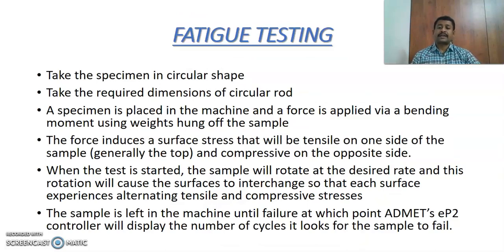We have to take the material in the required size and dimensions. The specimen is placed in the machine and the force is applied via a bending moment, and the force induces a surface stress that will be tensile on one side of the sample, and compressive on the opposite side. When the test is initiated, the sample will rotate at a particular rate, and this rotation will cause the surfaces to interchange, so that each surface experiences alternating tensile and compressive loads. So one side has tensile load and the other side compressive load. The sample is left in the machine until fracture. Finally the controller displays the number of cycles it took for the sample to fail. How many cycles it takes for the sample to fail, that is called the fatigue test.